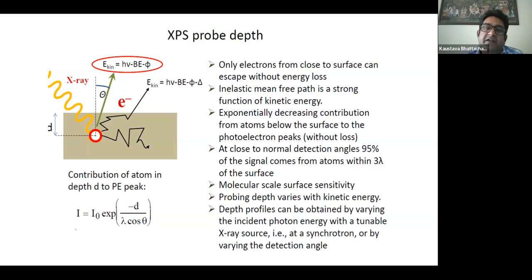So basically we are ionizing an electron, and the electron that can be ejected comes only from a certain amount of the surface. If we consider the bulk electrons, it is very tough to eject them, and also very tough to get the exact kinetic energy of those bulk electrons. So this system is sensitive to electrons up to about 5 to 7 nanometer depth of the system. That's the reason XPS is usually called a surface sensitive technique.